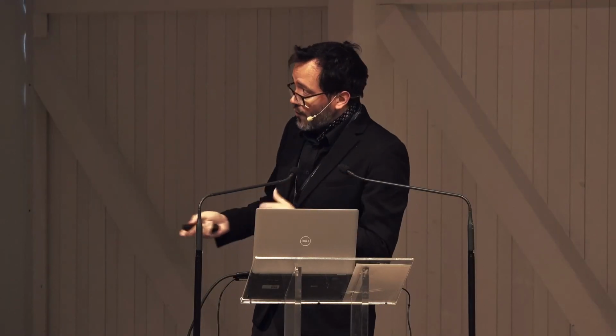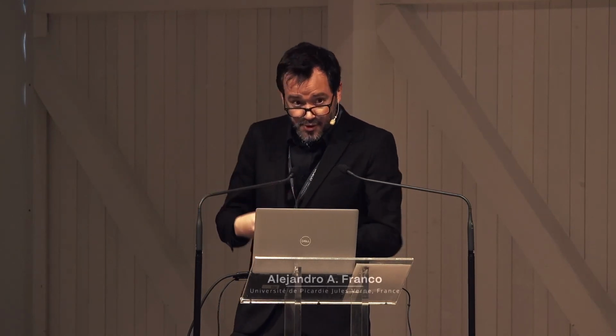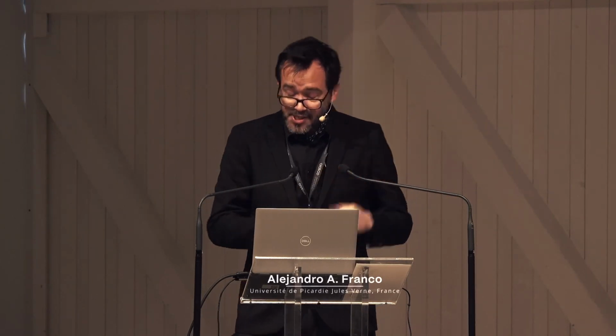Then we simulate the drying process. Then the electrode is formed, the microstructure in 3D can then be watched in the computer. Then we simulate the calendering. The calendering is the step where you need to press the electrodes in order to improve the electrical contact between the particles, because a battery is dealing with handling electrons, and therefore the electrodes have to have good electrical conductivity. That's why you press the electrodes with a machine called the calendering machine.